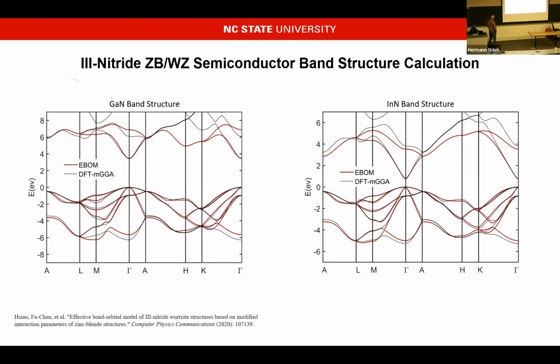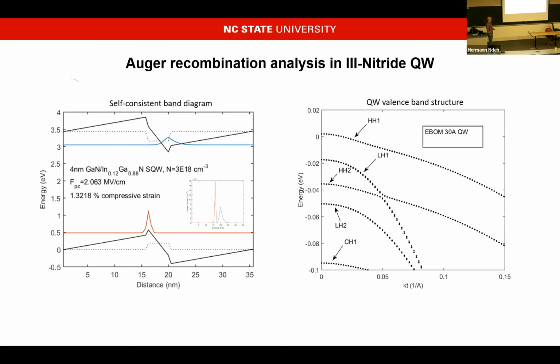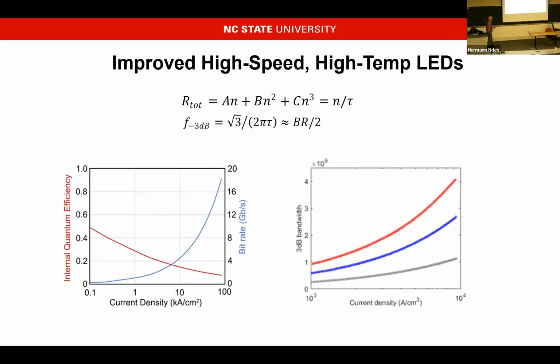So this is an example of work that Alex did for his PhD at Illinois, but basically he was able to, with this effective bond orbital model, match the DFT calculations with a calculation more than an order of magnitude more efficient. And so the work that we've done here is looking at what type of LED structures people are using for some of these high-speed LEDs, and developing a full band structure based upon this modeling capability. With that, we've got designs that would seem to indicate that we can more than double the bandwidth based upon what people have done, based upon the band structure and the calculation of the ABC coefficients that would come from that band structure.